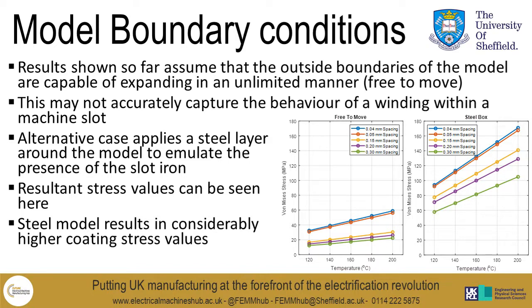So another parameter which is of interest is the boundary condition of the model. All the results we've been shown up till now assume that the winding can expand in an unlimited manner, and as a result, the outside surfaces are free to move. This is not an accurate representation of what will happen within a winding, within a machine slot, as there will be some constriction applied by the slot. An alternative model has been produced whereby a layer of steel is applied to the outside of the model, which emulates the presence of the iron slot. The resultant stresses from this can be seen on the slide on the right. What you can see comparing that to the free to move on the left is that in each case the stress is quite a bit higher when the constriction is applied.